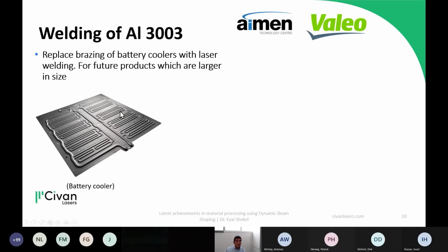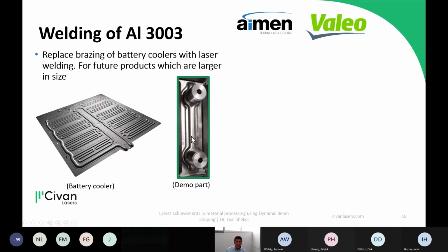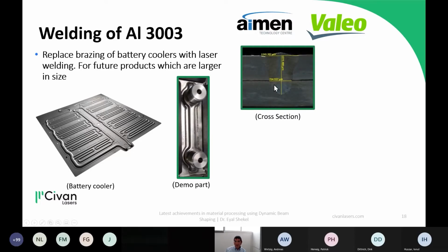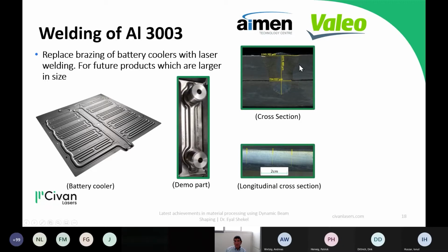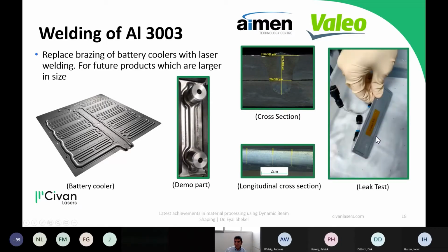And the idea is to take a battery cooler that is manufactured today with brazing and replace it with laser welding. So we got samples. This part represents the cooler, and we developed a very fast and very good weld with good geometry, good strength, no porosity, no spatter, at very high speed. You can see a longitudinal cross-section to see how stable it is. And of course, we did the leak test, and it's leak-free.